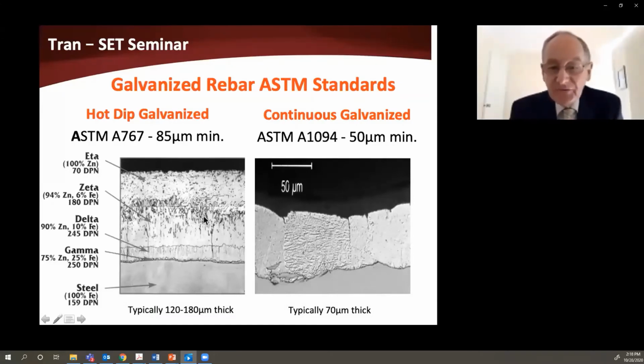Now, these two photographs here are fairly typical of the type of microstructure that develops with the different galvanizing processes. On the left, you've got the traditional batch galvanized, hot dip galvanized. And as you can see, it's made up of a series of alloy layers. Here's the base steel down the bottom. And then you have the zeta layer here. There's a gamma layer, the zeta layer. Key thing is there's a layer of pure zinc on the outside of this coating, which is typically 40, 50